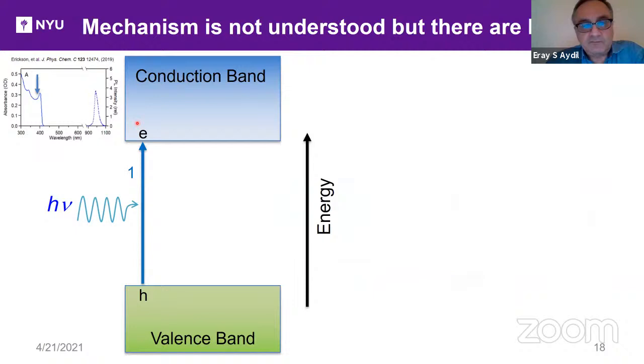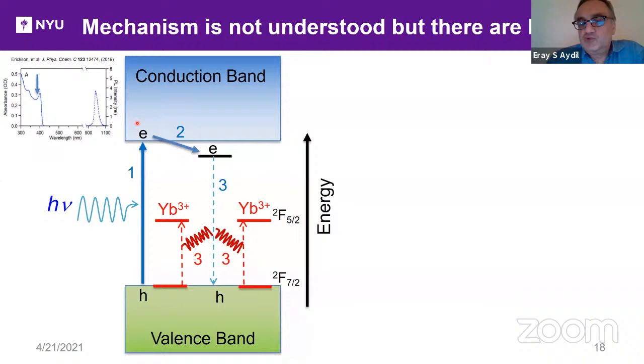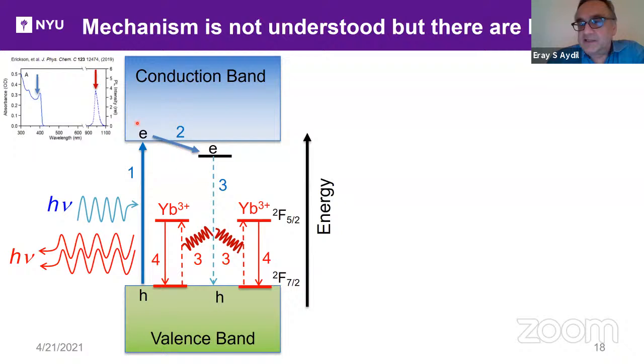Then that electron hole pair gets trapped in a defect, perhaps ytterbium induced or not. And then when that trapped exciton recombines, it transfers the energy to two ytterbium 3 plus, which then relax and emit the infrared light, two photons. And then you might say, well, two ytterbium have to be very close. The defect has to be very close.